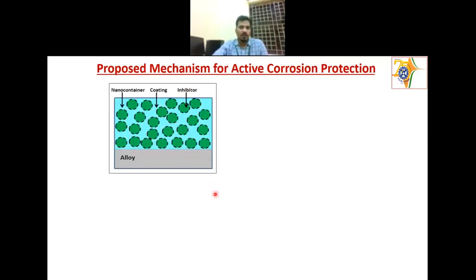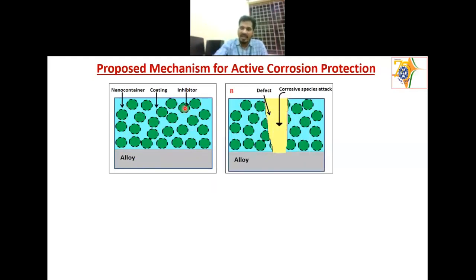So how do we propose a mechanism for that? This is our coating: you have the alloy here, and this is the coating, and the nanocontainer and inhibitor inside, the dark green being the inhibitor. If I have a defect I made here, then to the defect the corrosive species can come.